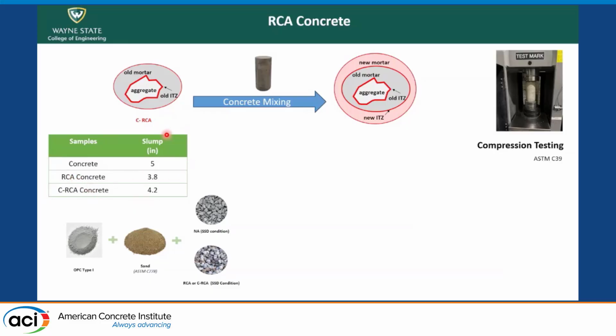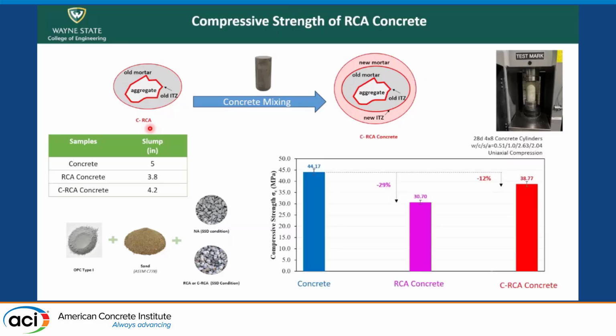Due to the difference in the water absorption, we also saw a difference in slump. And the way that we managed to combat this is to use SSD condition natural aggregates and SSD condition recycled aggregates.